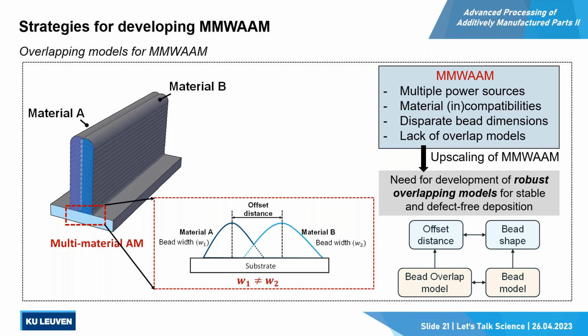When we are depositing overlapping beads, which have a common overlap area, the offset distance between these two beads is quite important. For a single material, this has been done and is quite well known in the literature, and there are some models, but we try to find the optimum offset distance in multi-material, between two materials. When we have two materials, the dimensions of these beads are different, the properties are different, so we need a new model to find the optimum offset distance.